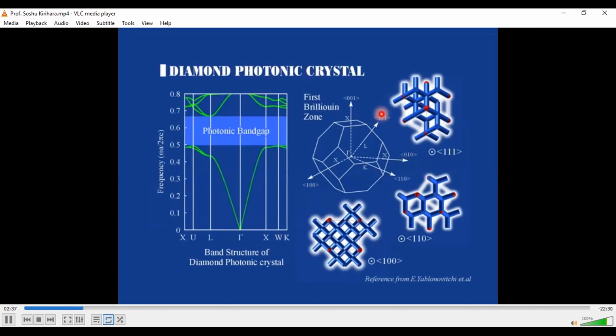One type is the diamond type, because diamond-type photonic crystals are able to open the photonic band gap for all crystal directions. This blue band shows the common region of the photonic band gap for all directions. So in this frequency area, electromagnetic waves are impossible to transmit in any direction of the artificial crystal. Of course, this photonic crystal is a perfect structure. However, it is difficult to fabricate such complicated lattice structures by using a conventional fabrication method.